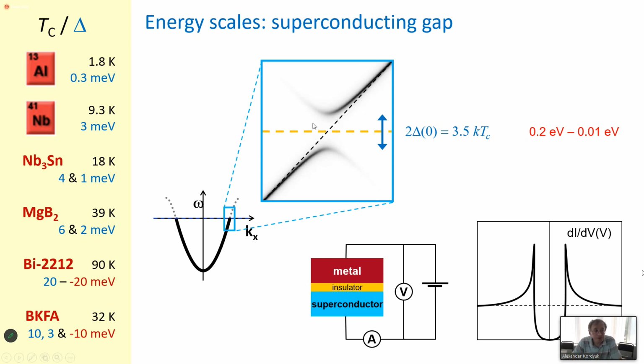And speaking more about superconductivity now and about scales in superconductors, we have the superconducting gap, which opens at the Fermi level, at the Fermi surface, and this is of the order of, let's say, from 0.2 electron volts, or from 0.02 to 20. It is a mistake here. 20 milli electron volts, down to very low values, and you see here just examples of known materials.